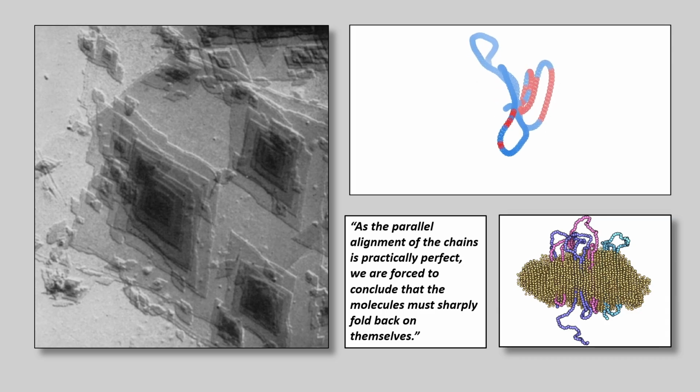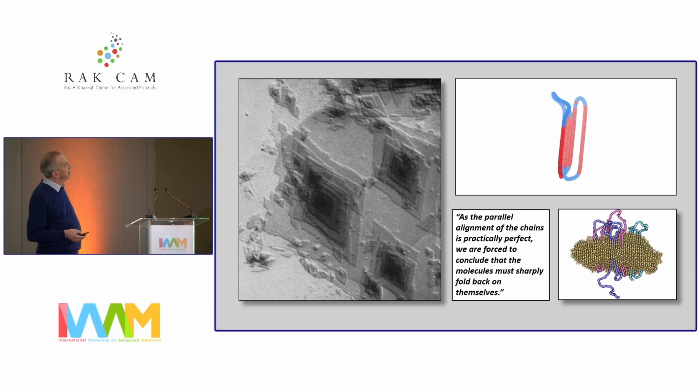So this is a microsecond simulation, and how you get to this final configuration of this particular molecule. And so it's a competition between inter- and intramolecular interactions, and it likes to be close packed, but it turns out to be just as profitable to fold against another part of the chain. And the coloring here indicates that it's actually got 6 neighbors around it. And so that is what happens in that nucleus.